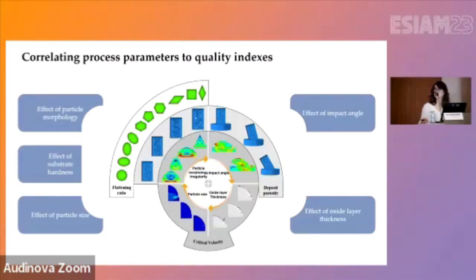Here we have performed single particle analysis in order to see the effect of the particle morphology, considering a range of regular and irregular geometries with different angles of impact, the effect of the thickness of the oxide layer around the particles, the effect of the deposition angle, and the effect of the substrate properties on critical velocity, which is probably the most important parameter that guarantees adhesion of the particles to the substrate during cold spray,